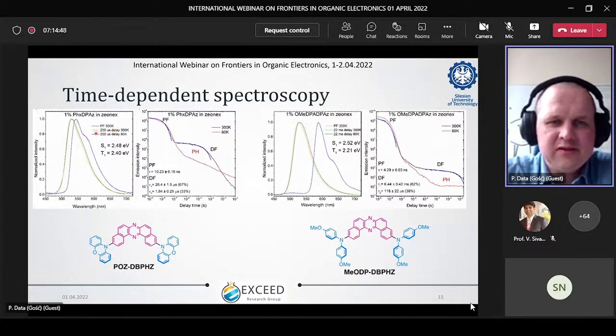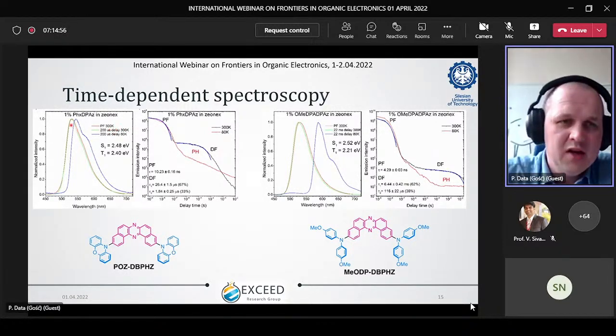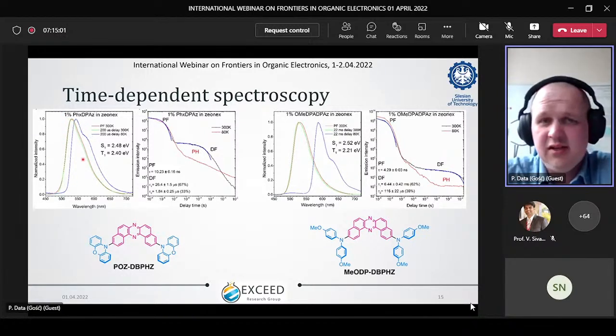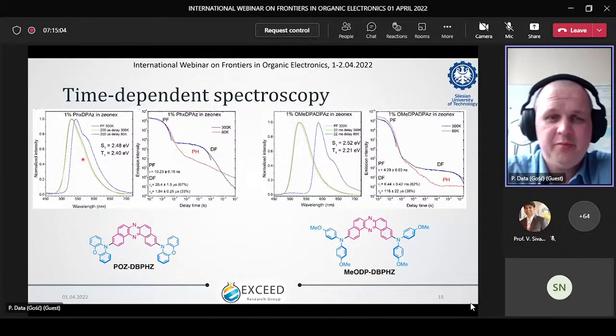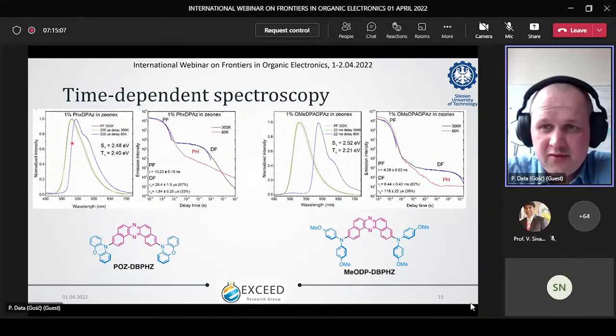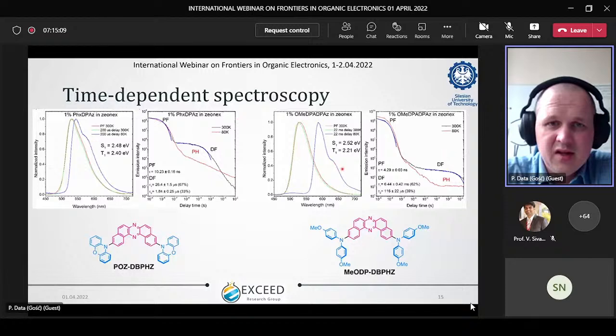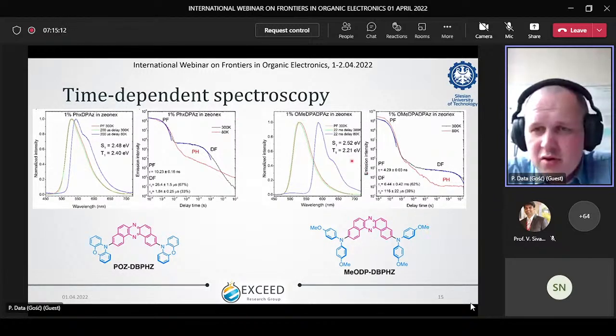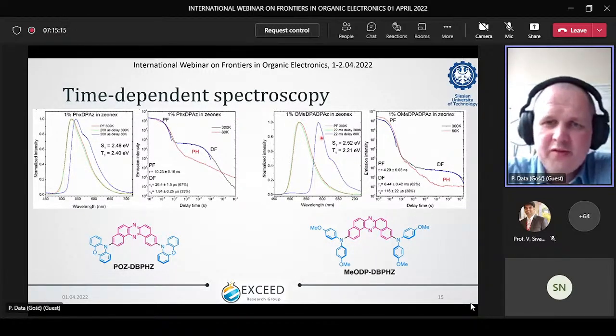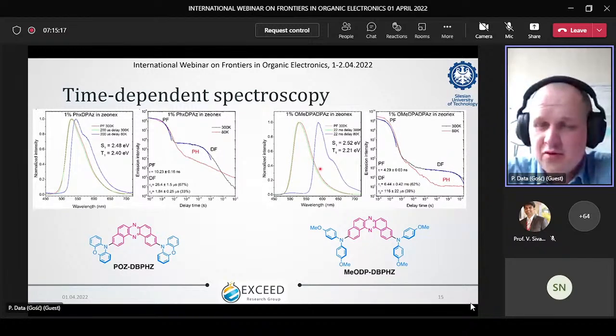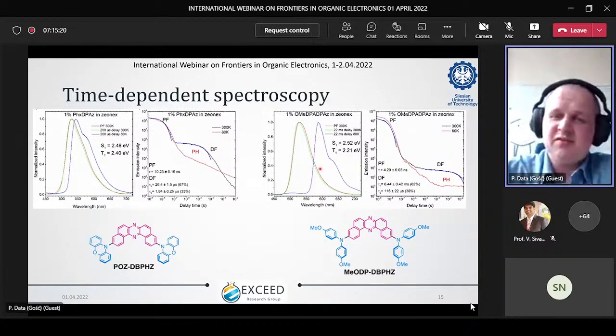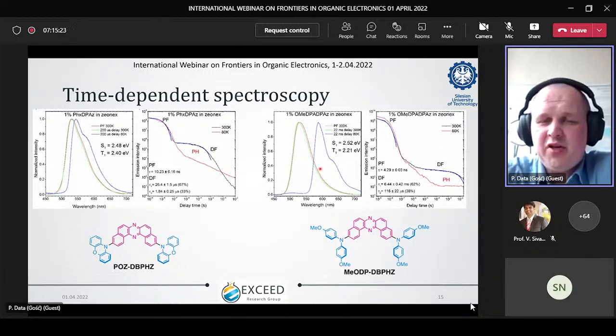And if we go to the same delay time where we saw phosphorescence, but at 300 K, so around room temperature, we see that our emission is almost the same like the fluorescence, and like I explained in the beginning, that means we have delayed fluorescence process. And in the case of the other molecules, we have similar behavior. We have phosphorescence and our delayed fluorescence, not the TADF. Remember, from this analysis, we can only estimate if we have delayed fluorescence process.